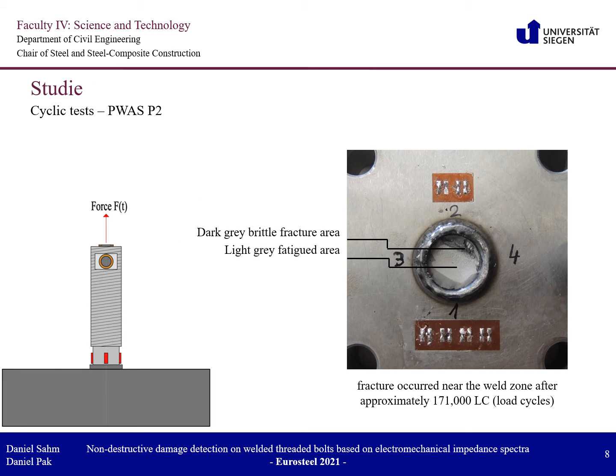Finally, I would like to present the results from the cyclical tests. In order to generate a fatigue crack in the area of the specimen's weld seam, the threaded bolts of the specimen were subjected to a cyclic axial load. For each specimen, in addition to the piezoelectric elements P1 and P2, which were already used in the preliminary test, 4 strain gauges were applied to the stud shank above the weld in order to record the surface strain in axial direction. You can see the strain gauges right here.